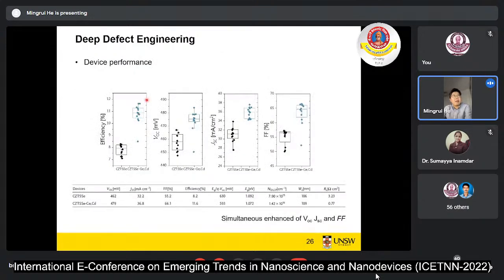After that, I made the device. As we can see, compared with the reference one without any doping or alloying, which only shows 8%, after doping the germanium and alloying the cadmium, the VOC, JSC, and fill factor, all three parameters, have been improved, which contributes to the final device performance.